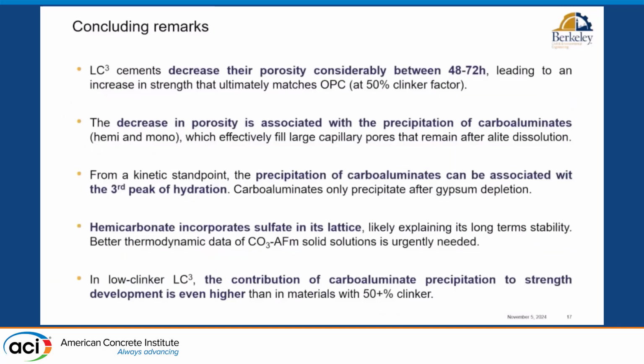So with that, I would like to move to my conclusion. LC3 cements decrease their porosity considerably between 48 to 72 hours. Again, this is the time period where the strength catches up with type 1, 2. And now we know that the reason for this decrease in porosity is associated with the precipitation of carboaluminates.